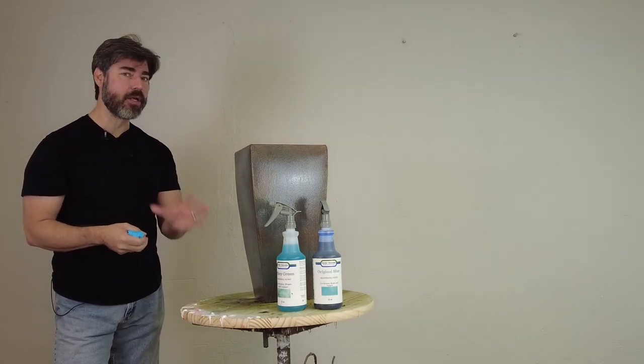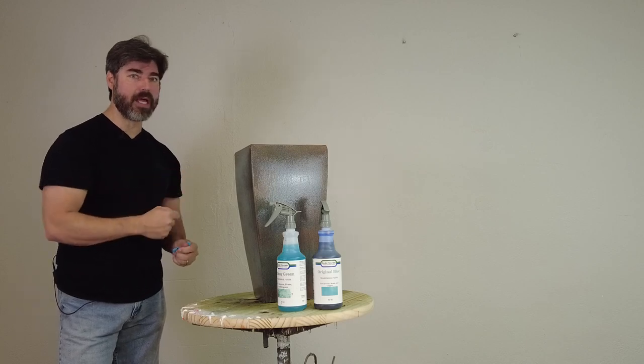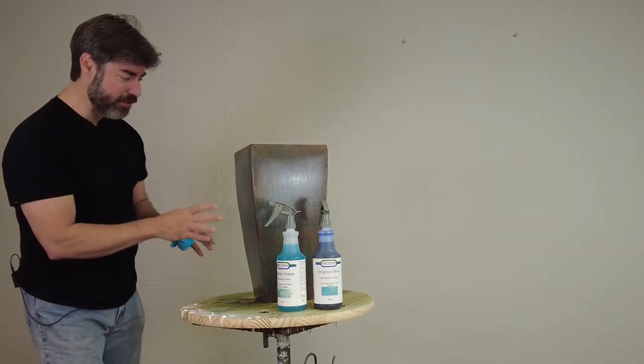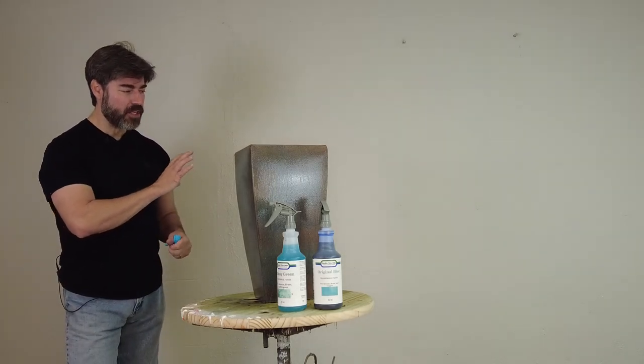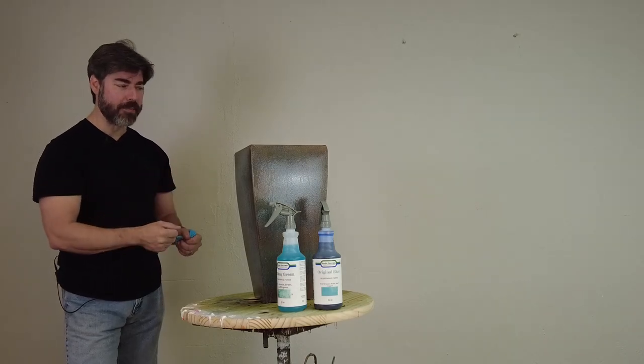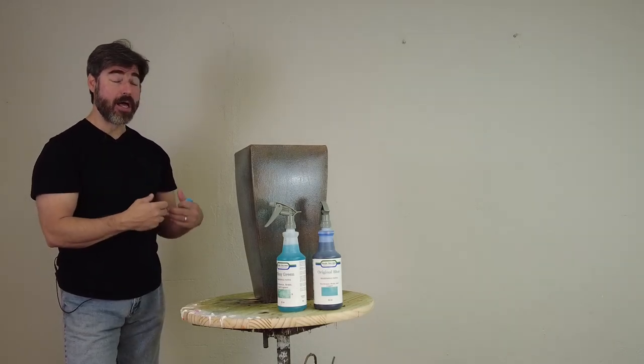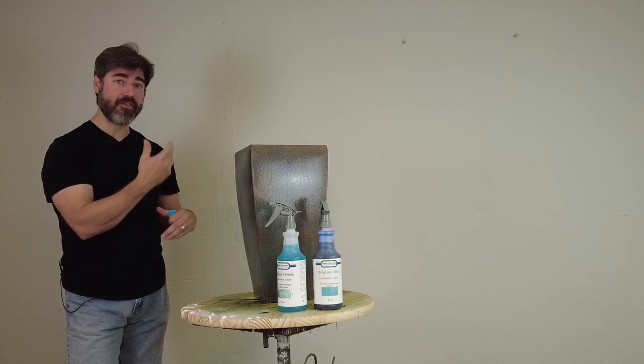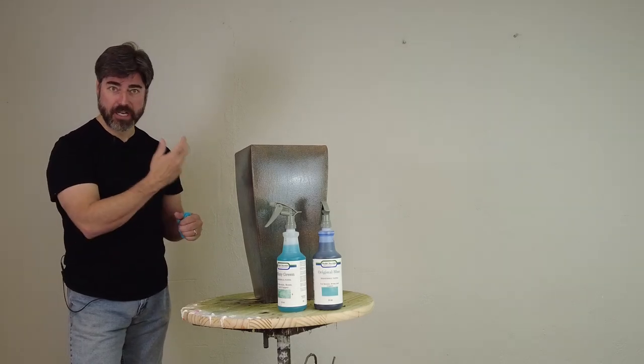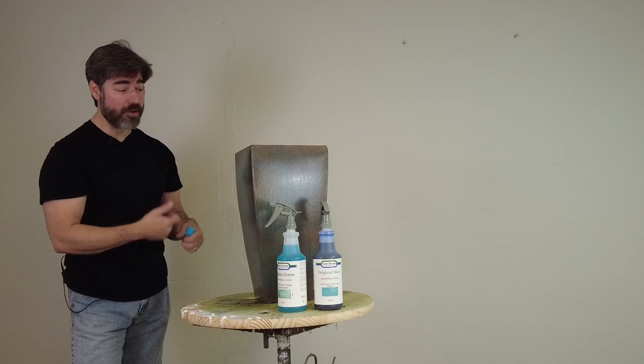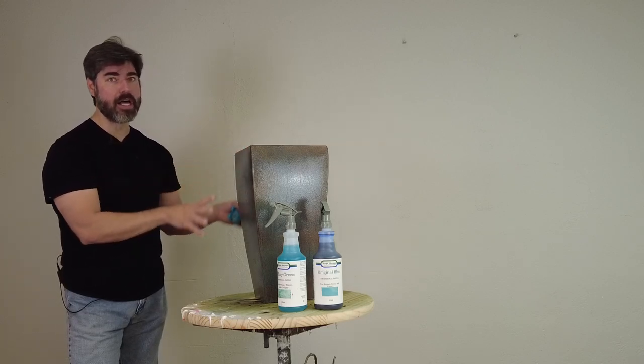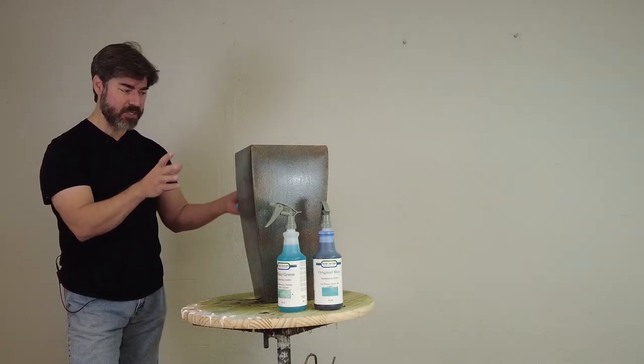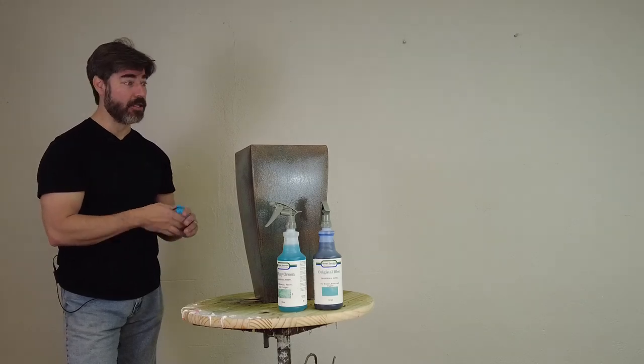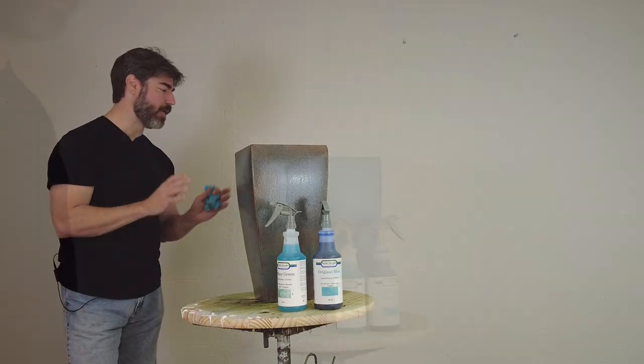And this is where you want to be really careful not to overapply your patinas. I've already put on probably a little more than I should have, but you want to take care that you're not overapplying, because if you apply too much, then you won't have enough oxygen on the surface to get a reaction. And also, if you put on a whole lot, you start to get a whole lot of runs. Now, a little bit of that sometimes adds to the look of a piece, but a lot of runs look sloppy, so be mindful of that.